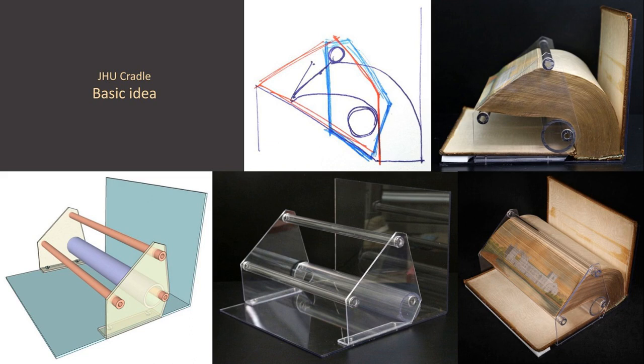A quick note on plastic materials in general. A few months after the Loyola-Notre Dame exhibit, the PETG sheets and tubes used were Oddy tested at the Walters Art Museum. While the sheets passed it, the tubes didn't. Unfortunately, simple labels like PETG or PMMA do not necessarily represent identical products.